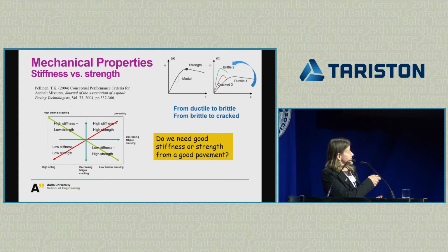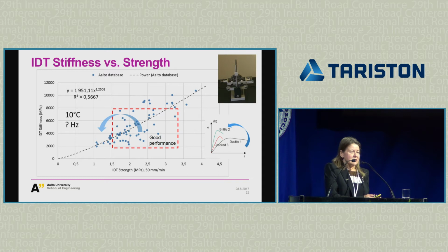But if you think about it, material goes from ductile to brittle, and when it gets brittle, it gets damaged. So we have these damage-based performance models and constitutive models. When there's damage, you see a decline of stiffness and strength for the material. If we take this idea, and this is just an example, we've been developing a database for different mixes in Finland. All these mixes are pavement cores, so we use the indirect tensile test to measure both stiffness and strength.